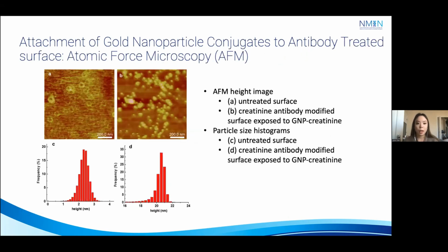And we also performed atomic force microscopy on the surface of our electrodes exposed to the gold nanoparticle attached to all three different metabolites. So in these images showing an AFM height image after exposure to the creatinine antibody, as well as the GNP creatinine, and then also the corresponding size histograms, which shows a greater frequency of around a 20 nanometer attachment or a conjugate onto its surface, which corresponds to the size of our GNP creatinine conjugates as observed in dynamic light scattering, UV visible, as well as a variety of microscopic techniques.